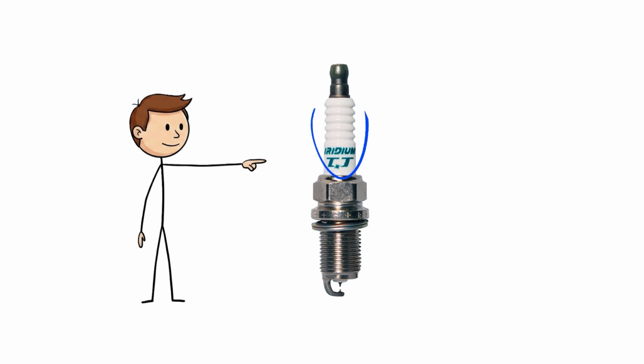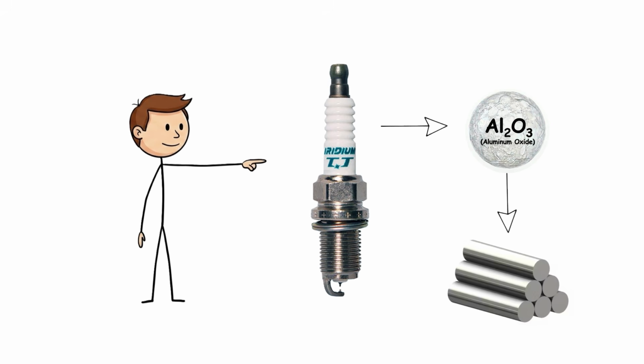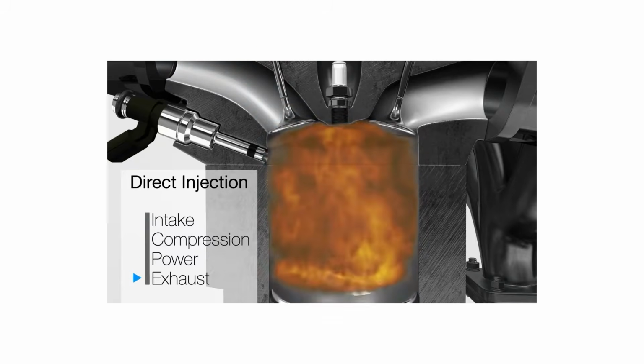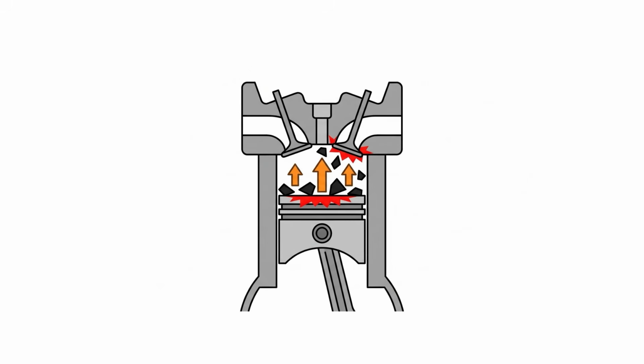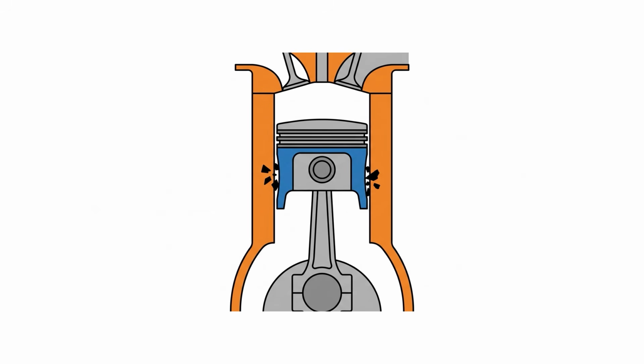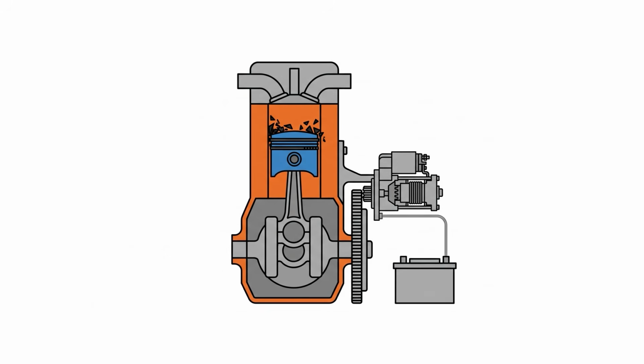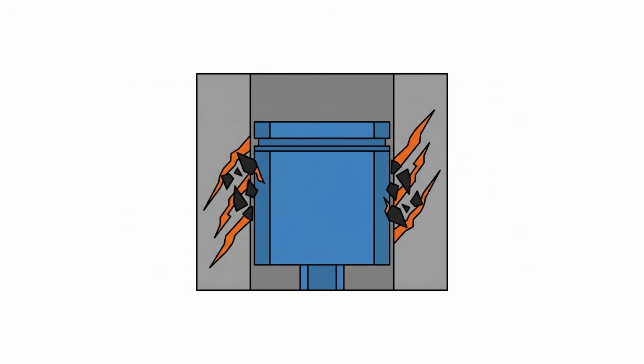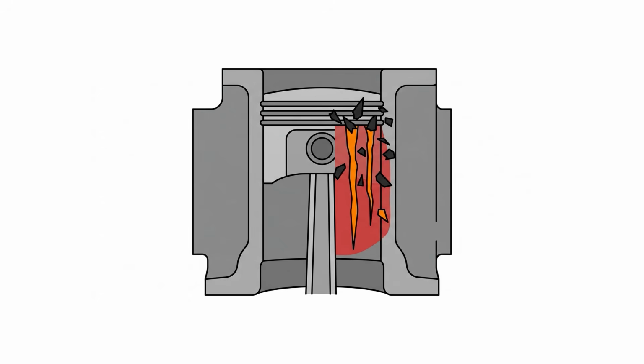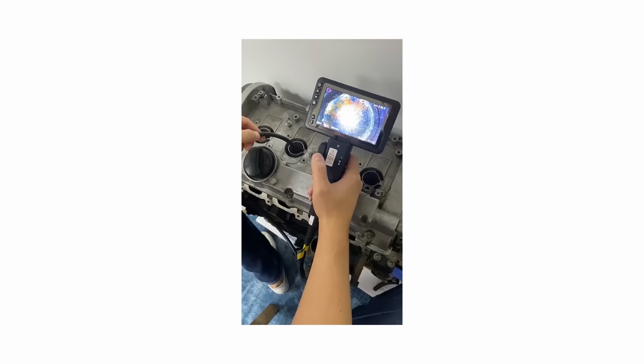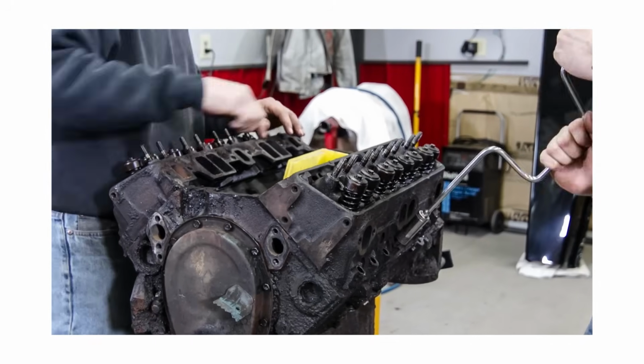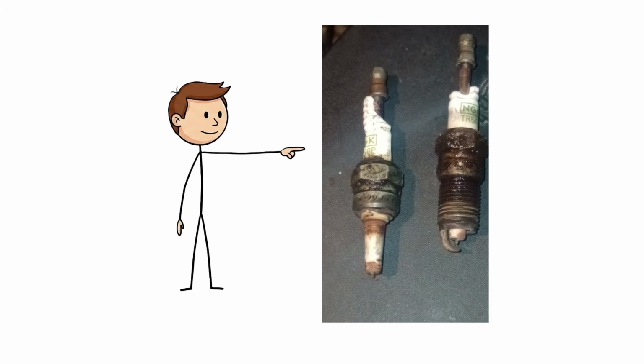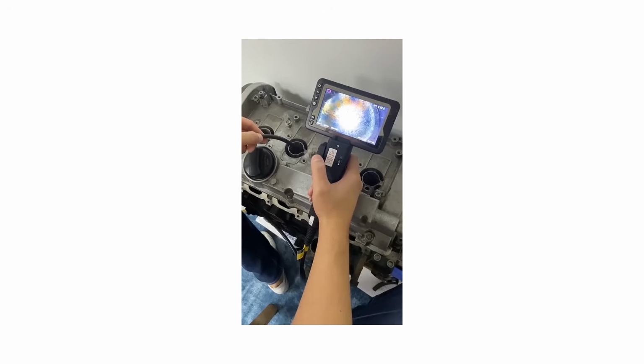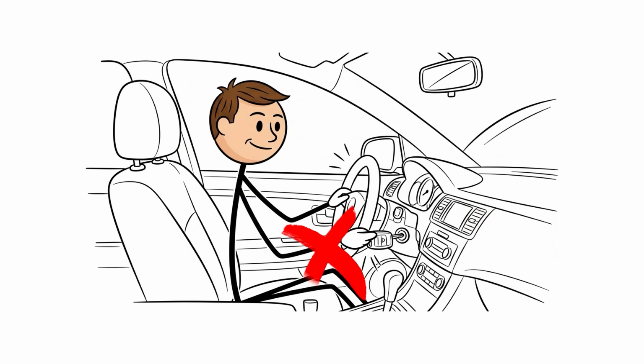Spark plug ceramic is aluminum oxide. It is harder than steel. It is harder than your engine block. When the piston comes up on the exhaust stroke, those ceramic shards do not gracefully exit the spark plug hole. They get caught between the aluminum piston skirt and the steel cylinder wall. As the starter motor forces that piston up and down, those ceramic shards act like diamonds carving glass. They gouge deep, irreparable trenches into the cylinder wall. A $300 mobile extraction job has just become a $5,000 total engine replacement. When a spark plug breaks and debris is in the hole, you stop. You step away, you use a bore scope and a specialized micro vacuum, but you never ever turn that key.